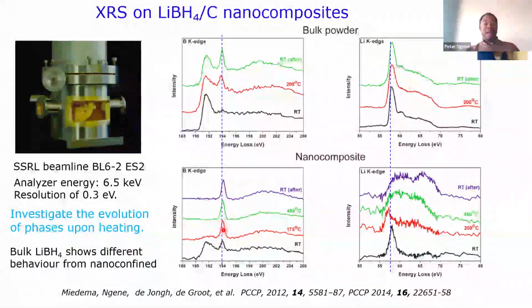So which means that already our sample, if this is the decomposition product, we're going to come back to that, already our sample is already decomposed. So when we cool it down at room temperature, we do see the same kind of thing again, that this remains. So the idea, okay, what is going on here? What is this particular peak around 194 eV?